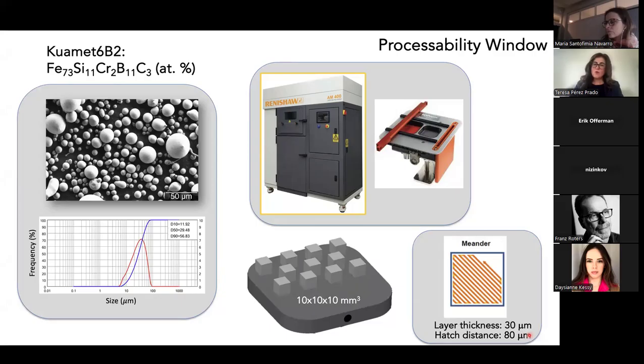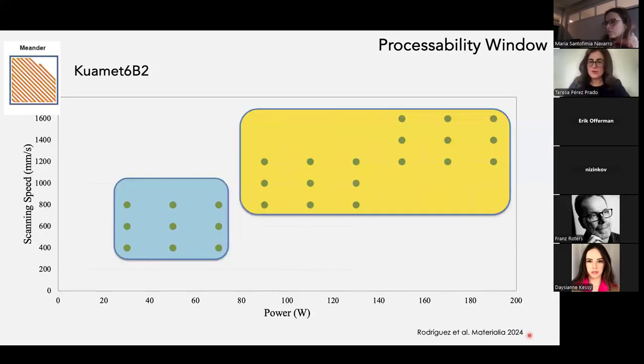These two are going to be fixed for the entire presentation. So we wanted to first analyze what is the processability window using meander scanning strategy for these commercial alloys, and I'll show you the results for Kuamet. What we did vary was the scanning speed and the laser power. And all these green dots here represent the parameter combinations that we tried.